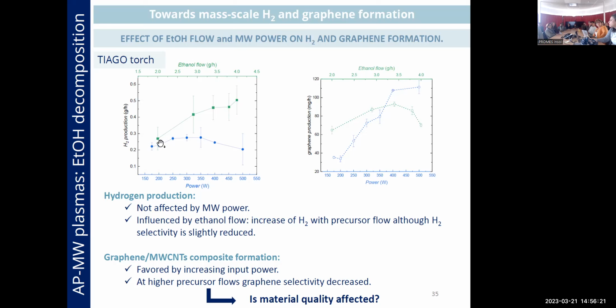We can see that the production of hydrogen is more or less similar regardless of the input microwave power. However, it was quite logical that increasing the amount of the precursor, increasing the amount of ethanol, increases hydrogen production. However, this increase is not linear. What does it mean? It means that the hydrogen selectivity decreases. So in that case, for higher ethanol flows, the formation of hydrocarbon gases is favored instead of hydrogen.